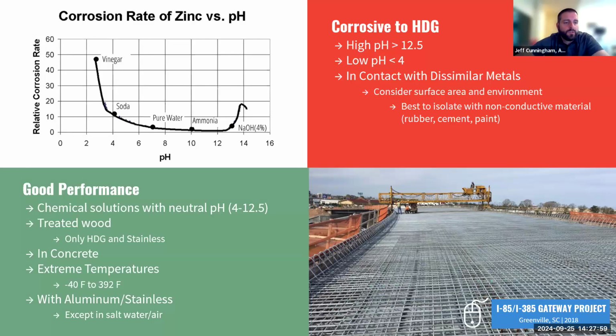It also works with aluminum and stainless, except if you're right off the coast with really salty air. Corrosive to hot dip galvanized steel are high and low pHs, and contact with dissimilar metal. Most of the time it's fine. You just want to isolate with a non-conductive material: rubber, cement, paint. You just have to consider how much of the surface area is in contact, and what kind of environment.